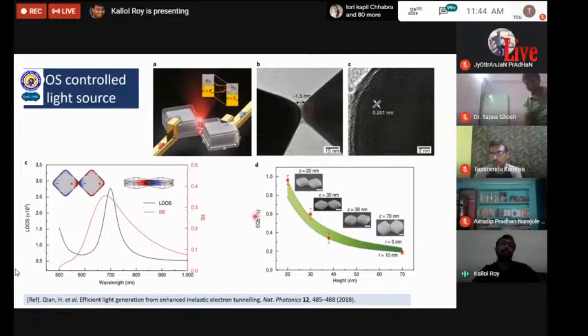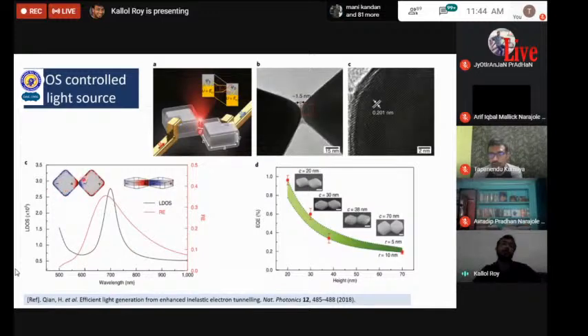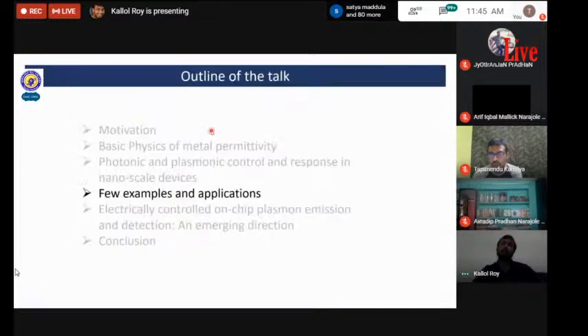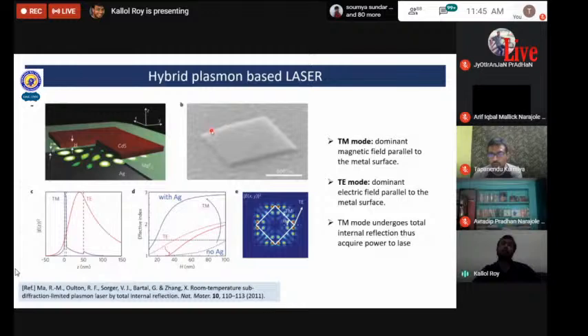You can see that the density of states is very high when two metals with sharp interfaces are placed a very small distance apart, of the order of only 1 or 2 nanometers. And quantum efficiency is getting higher, of the order of 1%, as the dimension in the Z direction, which is the thickness of the cube, is changed. So I'll quickly show a few more examples in this context.